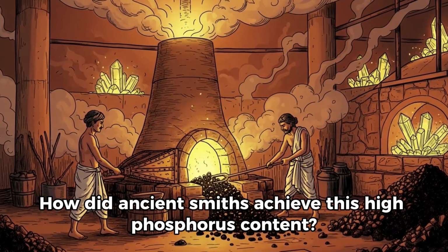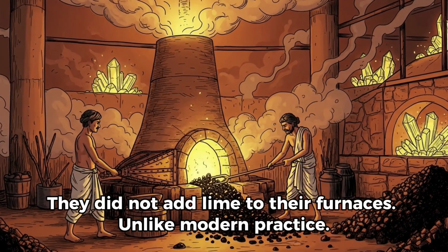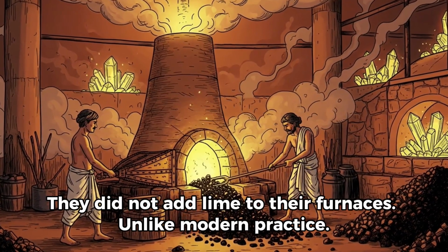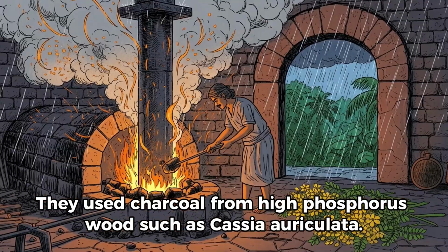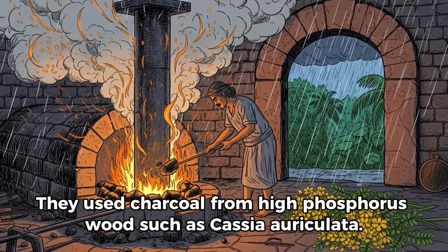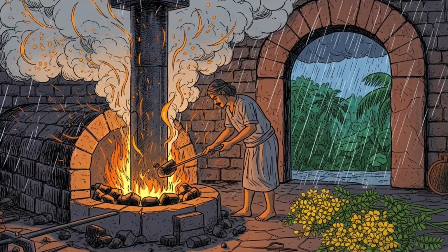How did ancient smiths achieve this high phosphorus content? They did not add lime to their furnaces, unlike modern practice. They used charcoal from high phosphorus wood, such as Cassia auriculata. Whether this was deliberate tradition or accumulated accident is debated. Low sulfur and manganese content further enhanced corrosion resistance.